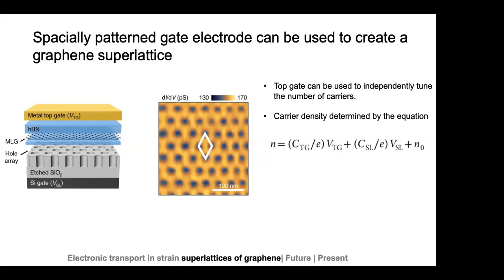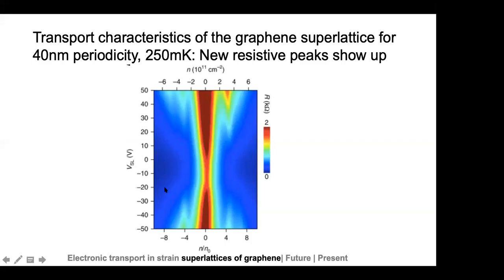So if you look at the resistance data of such a device, on the y-axis over here, you have the superlattice potential, which is the backgate voltage varying. And on the x-axis, you have the carrier density changing independently using the top gate potential. So for zero superlattice potential in the middle, you see that the resistance increases to a maximum as is expected for graphene and then decreases again. However, if you increase the superlattice potential, these additional features show up, extra peaks, and this is more evident if we take a cross section of this data.